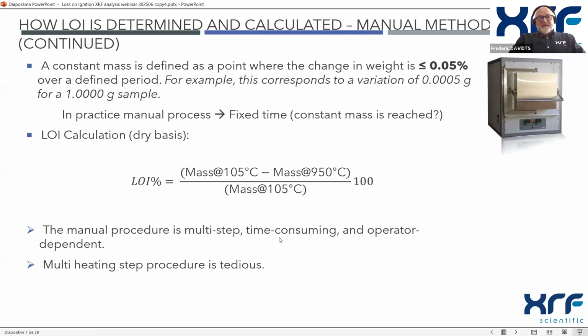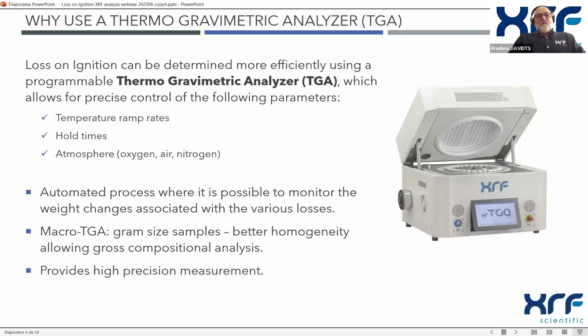And it starts to be tricky, complicated if you have multiple heating steps to do. So most of the time, you need to have many furnaces to do that separately. This is the reason to use a thermogravimetric analyzer, which allows a precise control of many parameters like the temperature ramp rates, the dwell times, the atmosphere. So this process is automated, and it's possible, of course, to monitor the weight change during the whole process and check the various losses of weight during the whole heating.